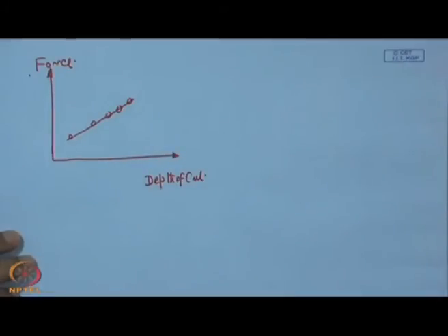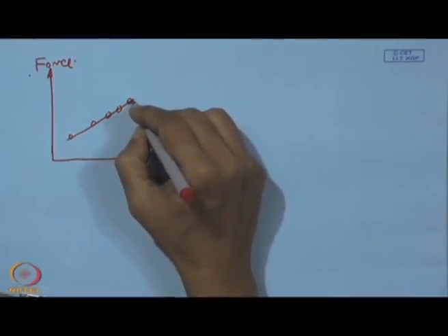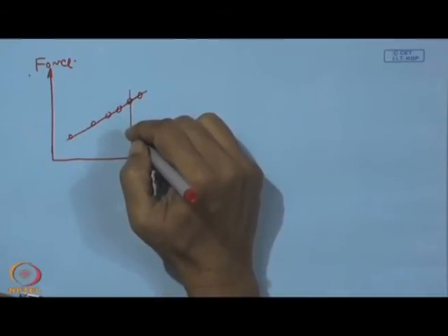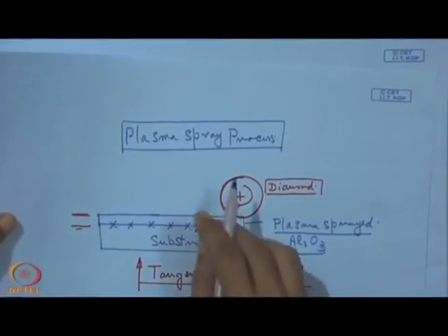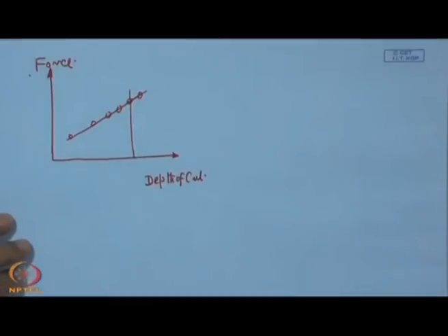So, it is quite satisfactory, but we can find that if it is the case that at certain point a part or whole of this chunk gets removed as a whole, as a layer, leaving that interface and exposing that substrate, in that case we can say that is the limit, and that causes the removal of this coating.